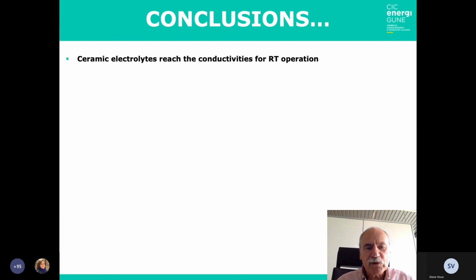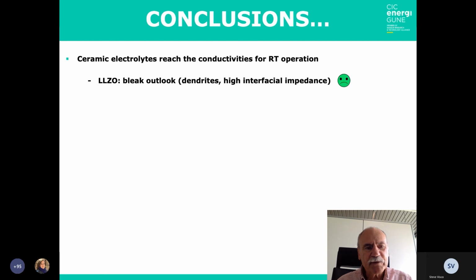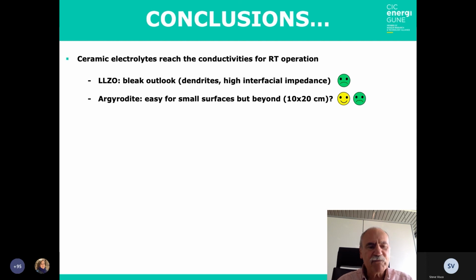Ceramic electrolytes reach the conductivity for room temperature operation. This is the base, especially the sulfides are the best conductors that one can imagine, possibly better than liquid. LLZO, the garnet, have a bleak outlook. They are sensitive to dendrites. They have a very high interfacial impedance. So it's not very nice, not very promising. Argyrodite, I mean the sulfide ceramic, are easy and work very well for small surfaces. But how are you going to make 10 by 20 centimeters of a brittle ceramic? This is a problem to solve, possibly by mixing them with polymers.